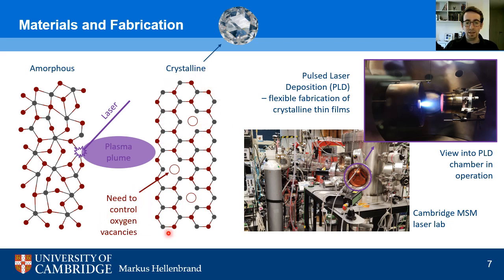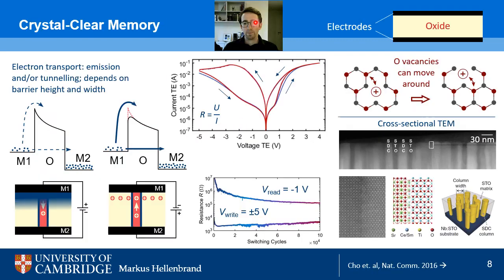So that means in the atomic lattice, in this nice crystal, there can be places where oxygen atoms are missing, and these are oxygen vacancies. And it is very important for the quality of the material and also for the functionality of the memory devices that we're trying to make to control the number of oxygen vacancies. This is one of the challenges of research, to get the conditions inside the vacuum chamber right to control the amount of oxygen vacancies. And with this, we finally arrive at the central slide, which explains how we are trying to realize new energy efficient forms of memory.